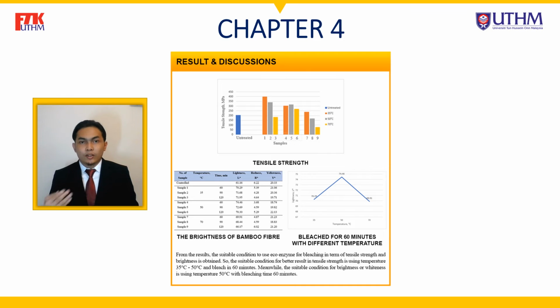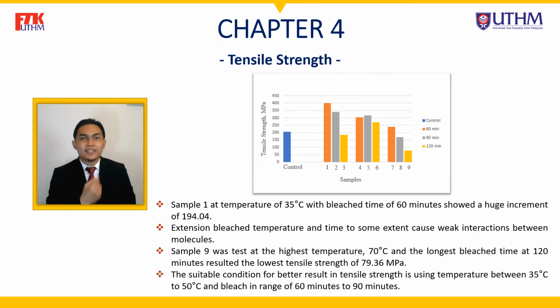The objective of successfully bleaching the bamboo fiber using a natural bleaching agent, which is ecoenzyme, is measured through the methods mentioned in the methodology, using the tensile strength and brightness of the bamboo. Based on the result for tensile strength, sample 1 at a temperature of 35 degrees Celsius with a bleach time of 60 minutes shows a huge increment of 194 compared to untreated bamboo fiber. However, the tensile strength starts to drop significantly when the bleach time increases for each temperature.